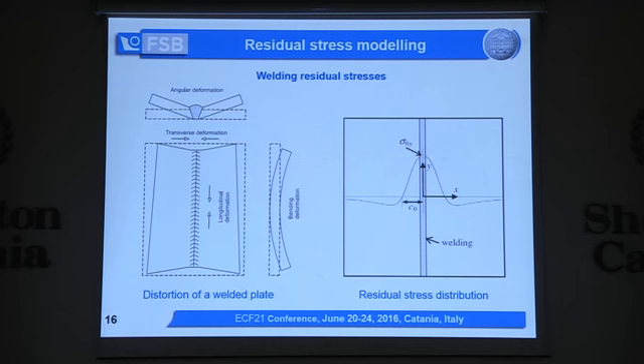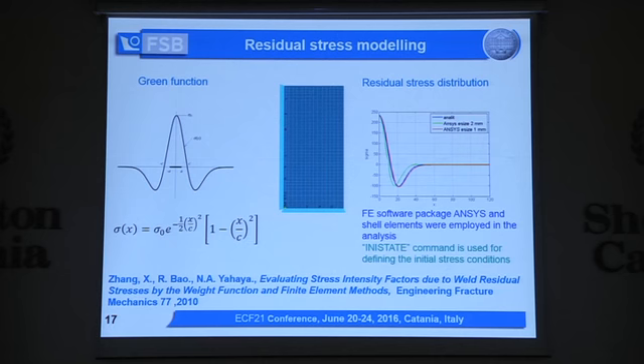And what we want to see, the influence of residual stresses on fatigue crack growth rate. If we have a welded plate, this is a typical residual stress distribution in longitudinal direction, where we here reach or may even exceed yield strength, and this area here makes equilibrium to this area, where here we have tensile stresses and here are compressive residual stresses. And the well-known function is so-called green function, and it's an analytical expression for this. These two areas below and above are equal, and we can